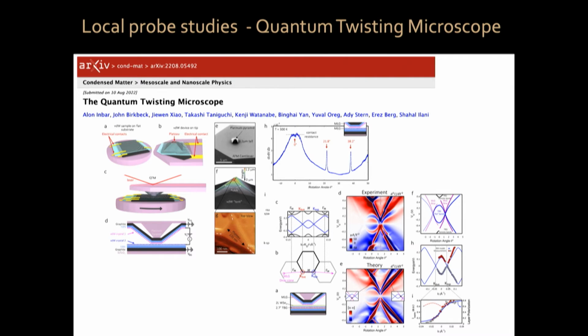More recently, something which is very amazing and has caught everyone by surprise is the fact that the group of Shahal Ilani at the Weizmann Institute has built something which they call the quantum twisting microscope. They have a sort of STM microscope. It's a tunneling microscope, but where they have one graphene sheet on the tip of the microscope and another graphene sheet or another 2D material on the other end, and they can put it on top and in situ rotate and measure the electronic properties as they rotate the system. This is something that is really extraordinary. You can see here some of those bands becoming flatter as they are rotating the system, etc.